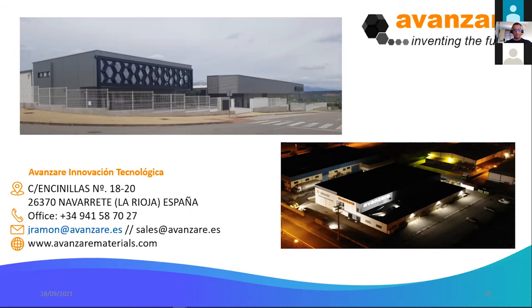Maybe this next question can help you focus on that. We tried it several times with carbon nanotubes, but the dispersion and the problem with the toxicity in Europe stopped the project. Can graphene solve these problems? Yes, because maybe the processability is higher with graphene. We added in one Banbury mixer more than 40-45% of graphene inside the recipe. With carbon nanotube, it's quite hard to get this high volume of additive inside the compound.